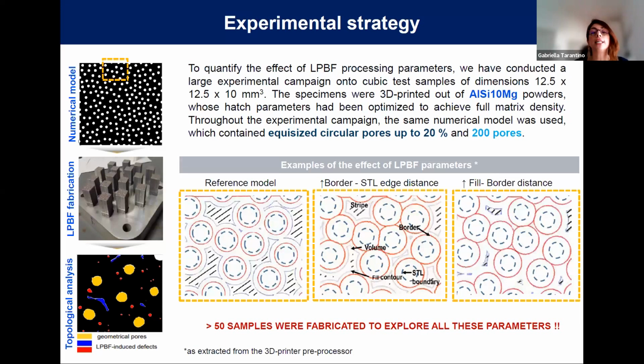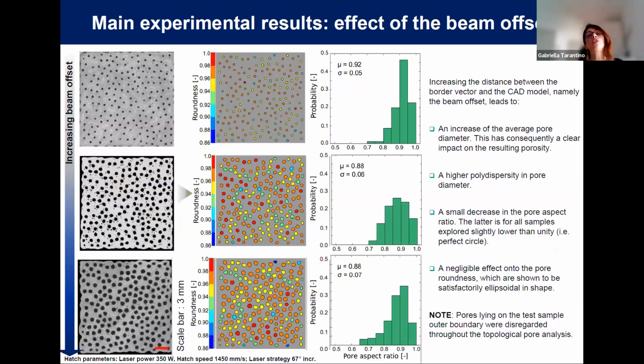So when we change the distance, the contour parameter, the actual mode, the actual result on the 3D printed part is pretty different. And to optimize these parameters and to analyze them via topological analysis, we ran a large experimental campaign taking one single numerical model which features on average 20% pores and contains about 200 pores, and we scanned all these possible combinations of the parameters. Now, to make a short story long, I'm going to just go to the main result of the experimental campaign before presenting a summary of the results.